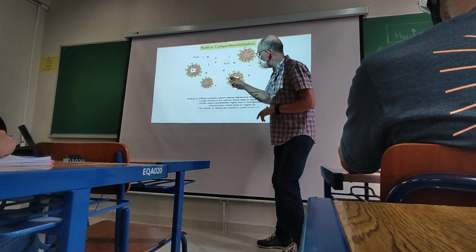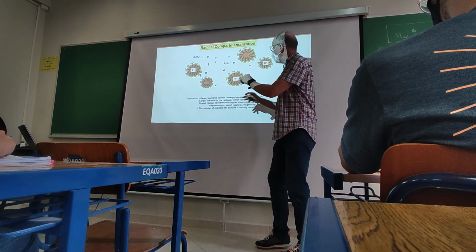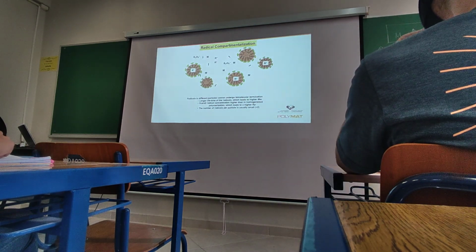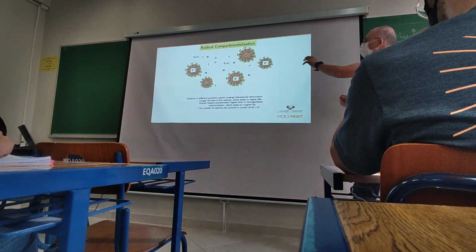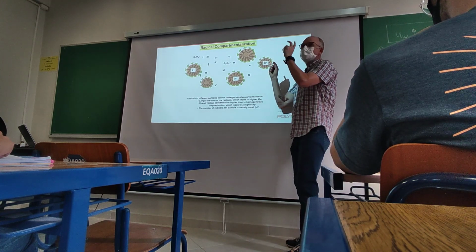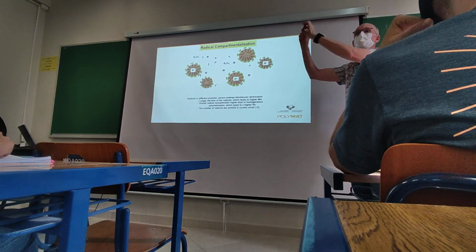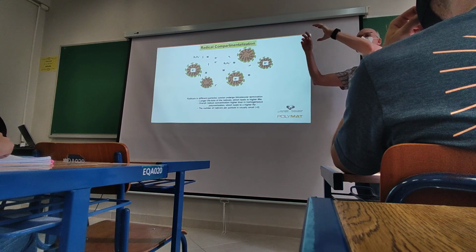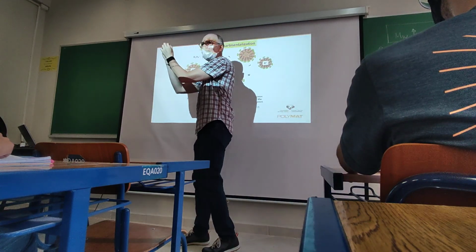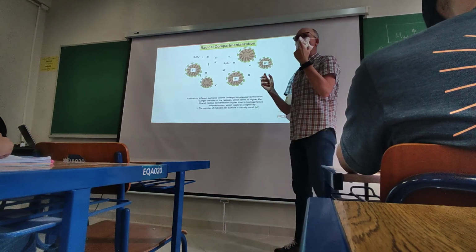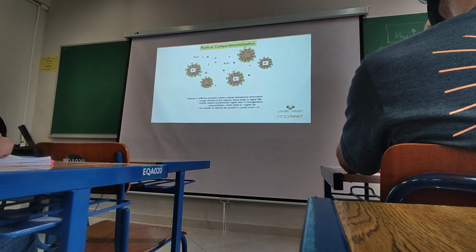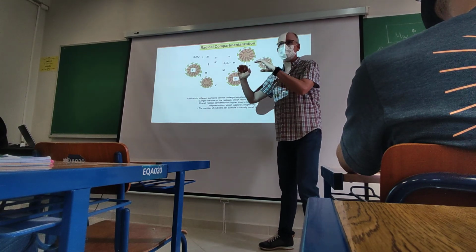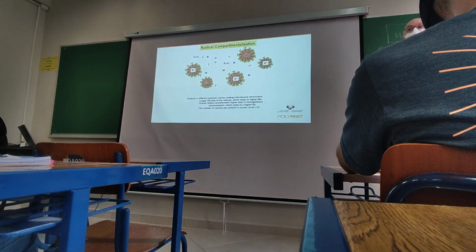And since the termination is reduced, a radical will grow inside of the polymer particles until another radical enters. The particles are so small that it's very difficult to have two radicals growing at the same time in the polymer particle. Okay? So when a radical is growing and another radical enters, there is almost instantaneous termination, so that the radical will grow until it is alone in the particles. So what will control the molar masses here is the entry rate of the radicals, more or less.